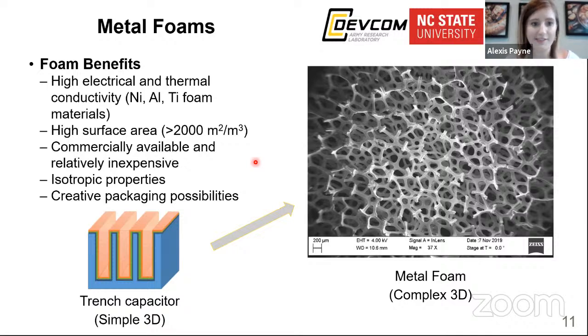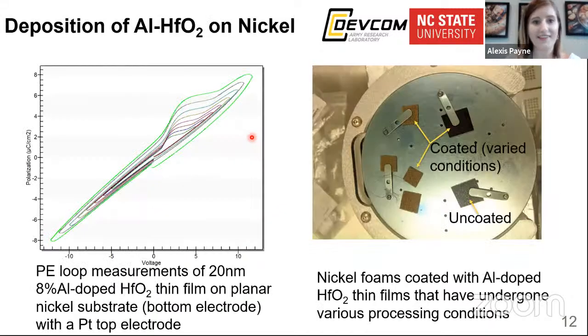Specifically, we use nickel, which is definitely cheap, or isotropic. So there's lots of different reasons why we'd want to use the metal foams. But again, we won't be current limited because we're dealing with a much thicker electrode base. So we have started work on this by depositing aluminum doped hafnia onto nickel.